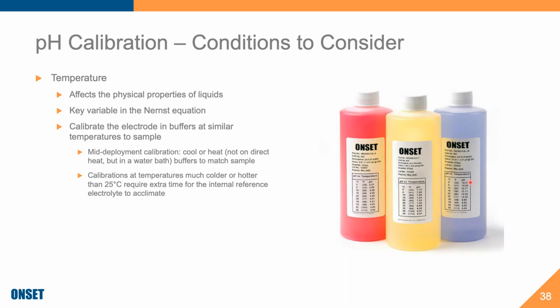So keeping that in mind, this also is a really good example of how pH 10 buffer has a very low buffering capacity, I know the irony is there, but it is easily contaminated. It will easily change its value. So one good best practice tip that I can give you is that even if you're doing lots of calibrations using pH 10, I would recommend keeping the bottles small, 500 mLs, maybe even a liter if you have to. But that way you're not having buffer sitting open for too long and then getting contaminated just by the air. pH 10 will change its apparent pH just with the CO2 that's present in the air over time. So keep that in mind when you're storing your pH buffers.